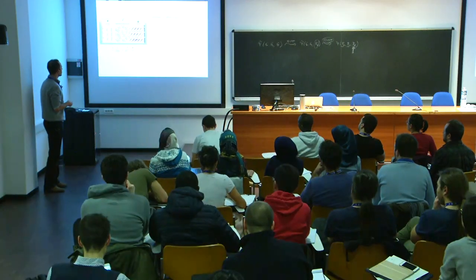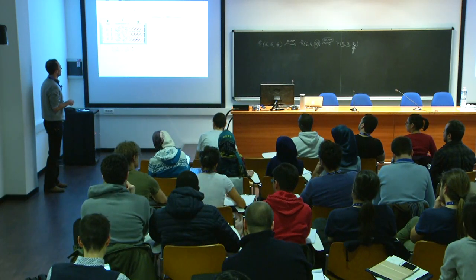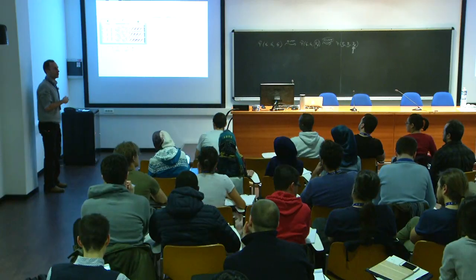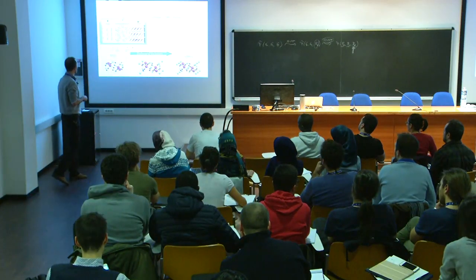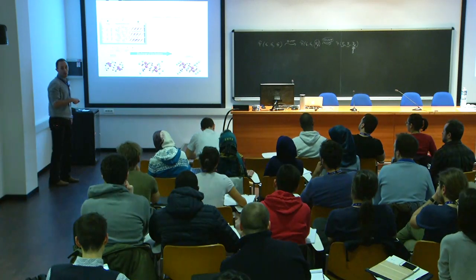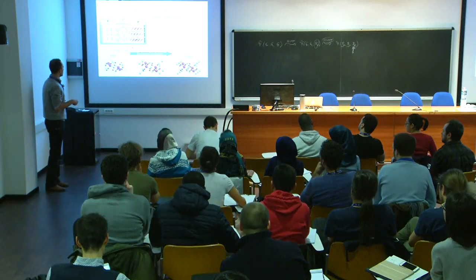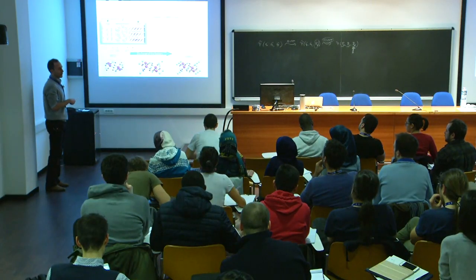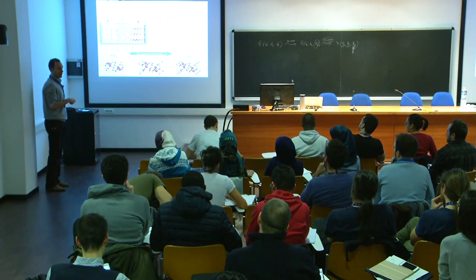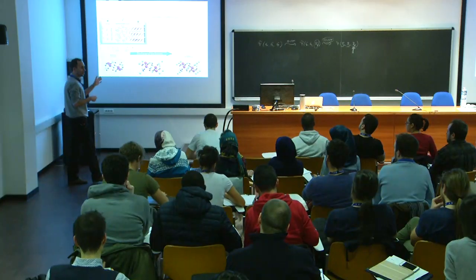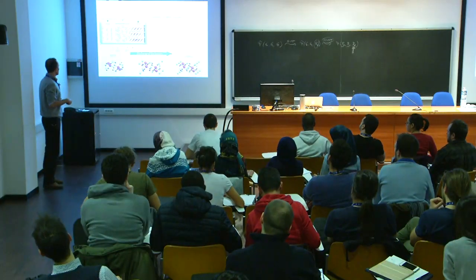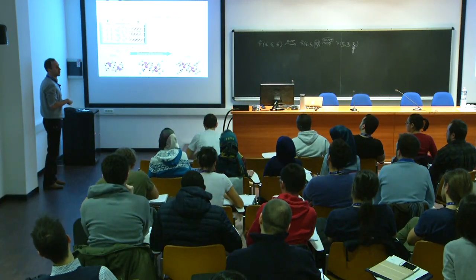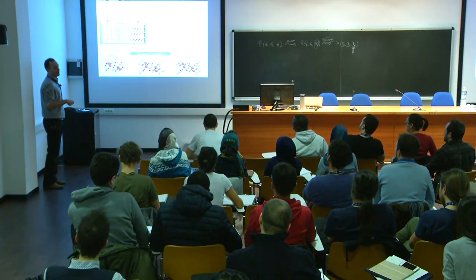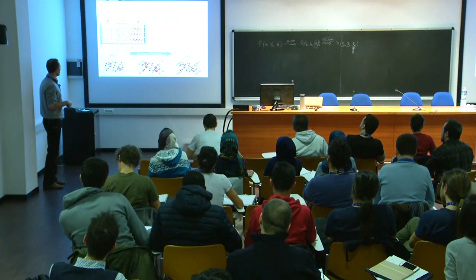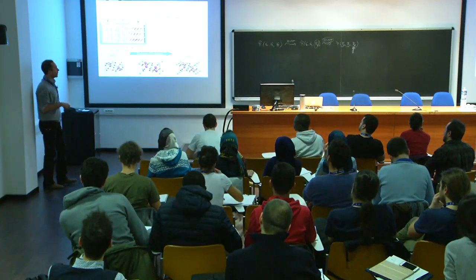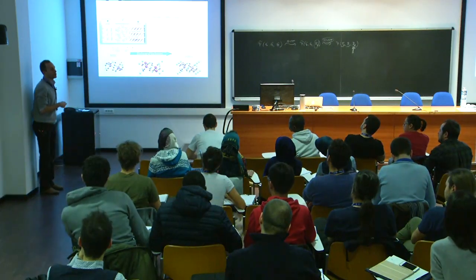This is another case, something that I'm actually working on: cathode materials of lithium-ion batteries. These are also transition metal oxides. In particular, I'm working on these lithium transition metal phosphate olivines, which means that they have an orthorhombic structure. The problem here is to capture electronic localization in dependence of the amount of lithium that you have in your structure. During the discharge of the battery, lithium moves from the anode to the cathode. So you have a different amount of lithium ions in the cathode along the time, during the discharge, and you see that the cathode material switches from this state, which has no lithium inside, to this other phase that has plenty of lithium inside, and correspondingly, the transition metal switches from 3+ states, if you do the math of the stoichiometry, to 2+ states. And this switch is actually what powers the battery.